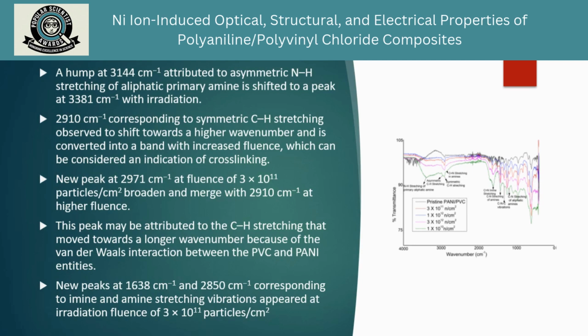A new peak at 2971 centimeter inverse at a fluence of 3 into 10 power 11 particles per centimeter square has broadened and merged with 2910 centimeter inverse at high fluence. This peak may be attributed to the CH stretching that moved towards the longer wavelength because of the van der Waals interaction between PVC and polyaniline entities due to irradiation. Other peaks at 1638 centimeter inverse and 2850 centimeter inverse, corresponding to imine and amine stretching vibrations, appeared at an irradiation fluence of 3 into 10 power 11 particles per centimeter square.